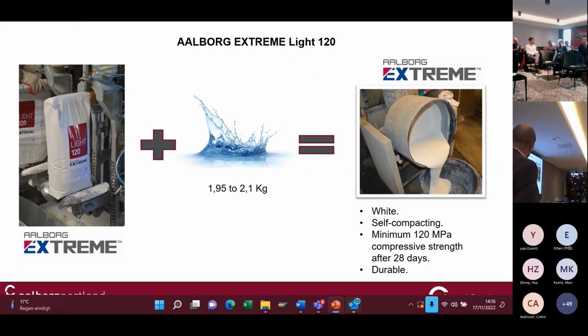So the principle is very easy to use. We have the Aalborg Extreme in bags of 25 kilo, or also available in big bags, 1 ton. The water dosage is something that is very fine-tuned, also in the lab. So let's say that the range of water dosage is very narrow, and you have to respect it to be sure that also the performances you want to achieve will be achieved. And so the compressive strength for this product is minimum 120 MPa.